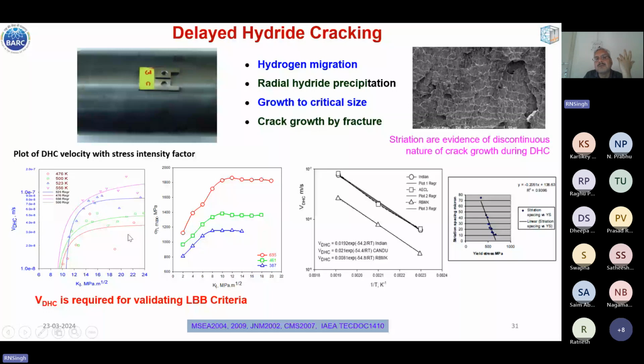Here we saw a plot of material from different sources. Both our material and CANDU pressure tube material are almost overlying. Here, the first two curves are almost overlying on each other, whereas the Russian material, which is produced by heat-treated tube, has almost half to one-third of the DHC velocity.